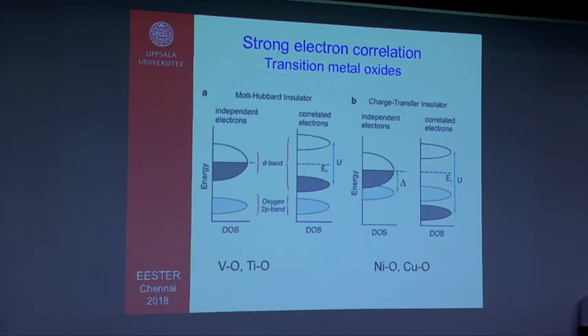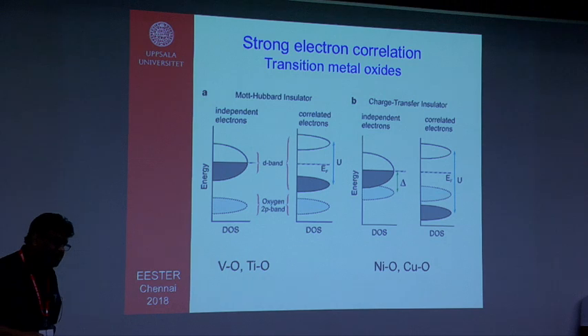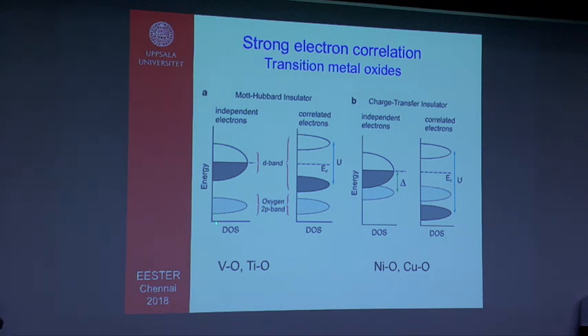So one of the typical examples is actually transition metal oxides. For example, nickel oxide, manganese oxide, there are many different oxides. So you can classify them as Mott-Hubbard insulators or charge transfer insulators depending on what are the relative positions of the d and the p electron states there. If you look into this side, this is a schematic diagram of the density of states. So this is independent electrons, or sometimes people call it non-interacting picture, because this comes from LDA or GGA. You see that this is the d band, and the Fermi level is passing through the d band, telling us that this is metal. But in practice, this is not a metal, this is an insulator or a semiconductor.